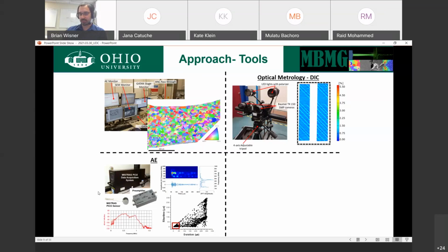Acoustic emission, on the other hand, is a passive technique. It's basically what you guys are doing right now. We're just listening for a change. That change can happen anywhere in the volume. And so long as the material is conductive enough that the wave can reach the sensor, we detect it. That means we can see damage that happens below the surface. That is extremely helpful if we're trying to understand what's happening in manufacturing processes. A lot of the defects that occur will happen below the surface, and you won't see them if you don't have some method that allows you to probe there.